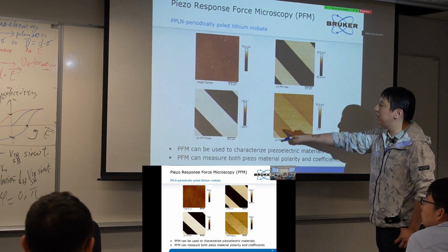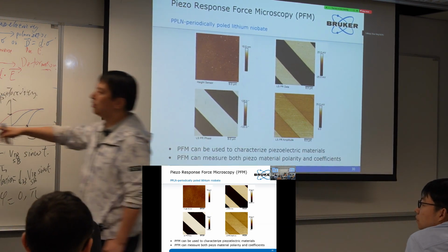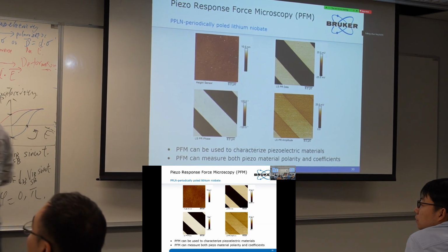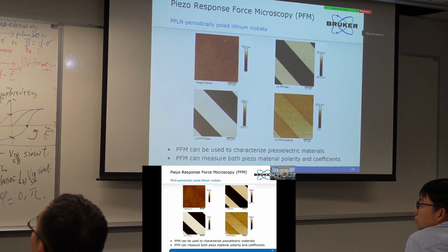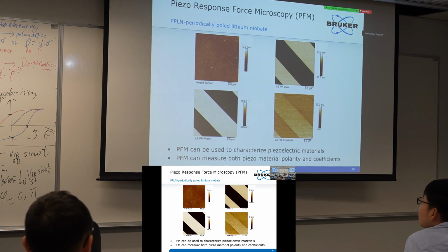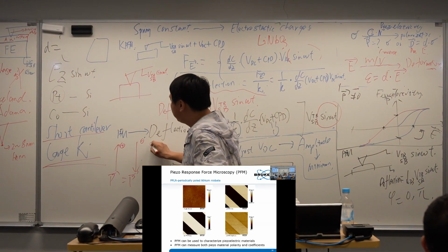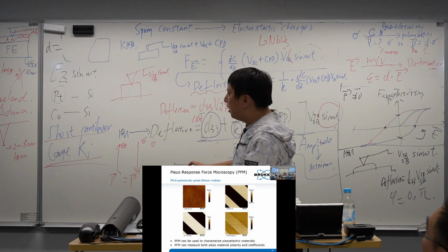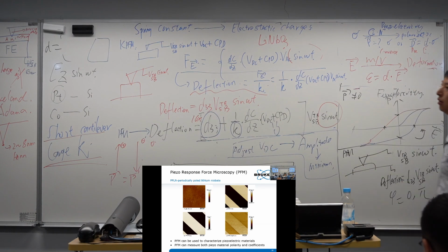We get results like this because we have electrostatic charges. Why? Because we're facing up and facing down. The polarization is the same, but facing up and facing down, we expose positive charge or negative charge differently. And you know, in our atmosphere, in our air, they are not the same. Positive charge and negative charge don't attract the dust completely the same.